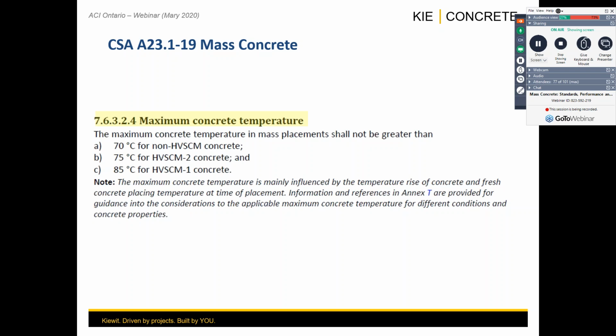What we did in this case is, in consideration that we're not going to be able to have all the specifics of the concrete mix proportions, but we know that the mix design submittals are going to identify their high volume SCM-1, high volume SCM-2. That's information that is known. There's no intent here to provide to the user any of the proprietary information from the mix proportions by the concrete producer. So what we did is, in consideration of the benefits of high volume SCMs, we allow increasing the maximum temperature for mass concrete if you go to HVSCM-2 or HVSCM-1.